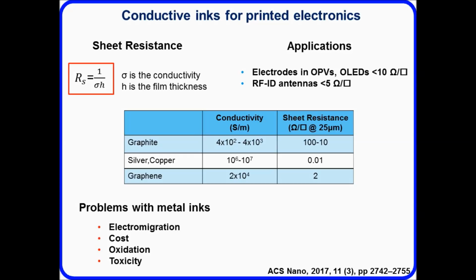With graphene-based inks, the best performance that we've got so far is around 2 ohms per square at 25 microns thickness. So until recently, the challenge for graphene has been with the scalable production methods, and that's where microfluidic production has really helped and now should help us to be able to drive down the cost of graphene inks and graphene production.